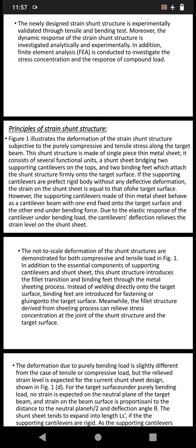In addition to the essential components of supporting cantilevers and shunt sheet, these shunt structures introduce the fillet transition and binding feet through the metal sheeting process. Instead of welding directly onto the target surface, binding feet are introduced for fastening or bonding to the target surface. Meanwhile, the fillet structure derived from the sheeting process can relieve stress concentration at the joint between the shunt structure and the target surface.